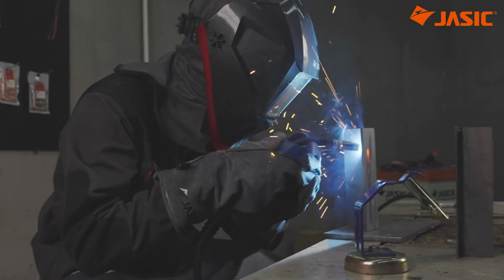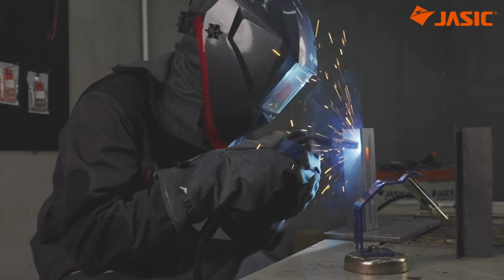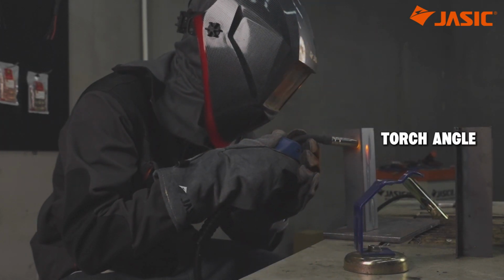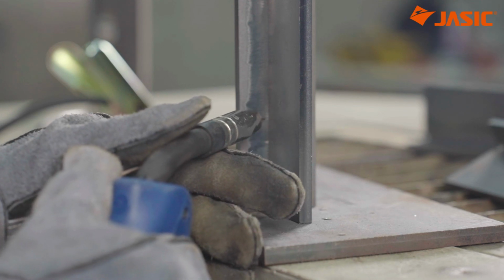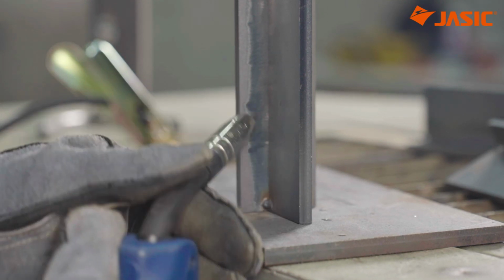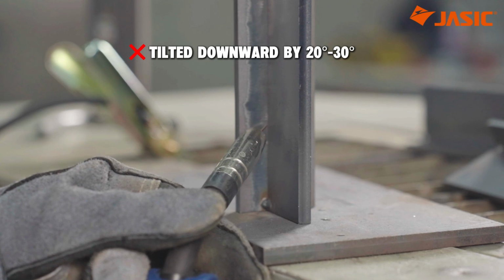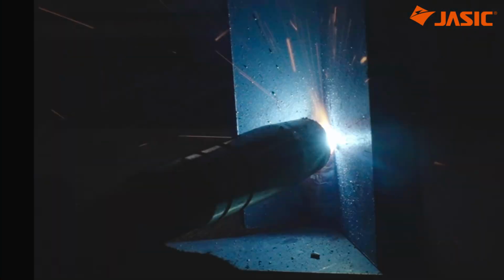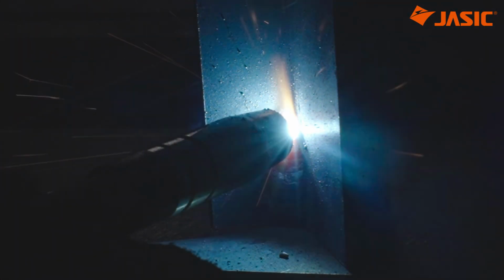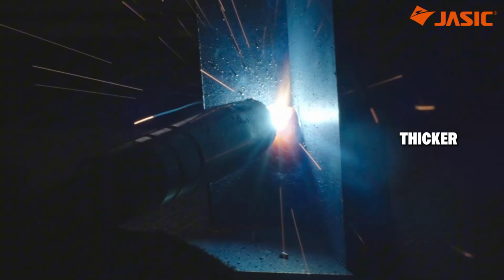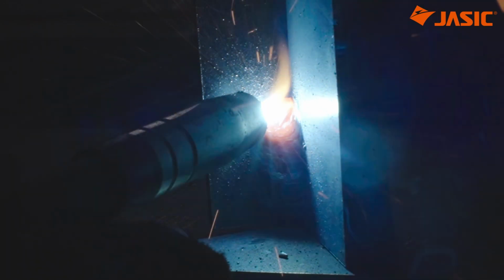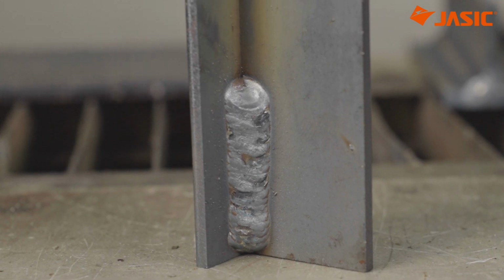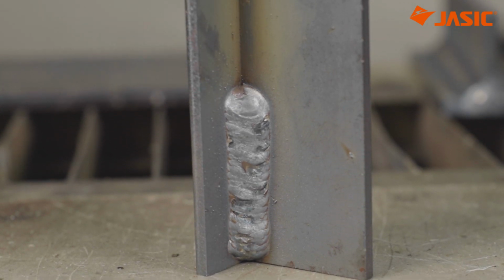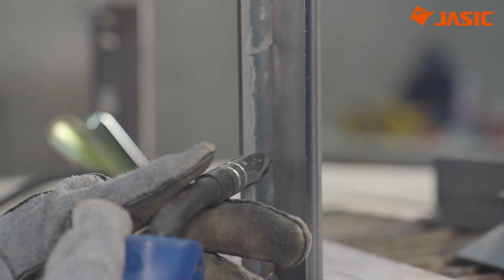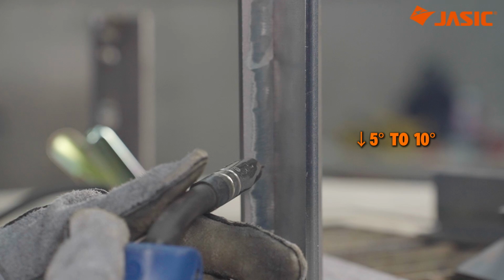If you find that you're having trouble moving the weld upward, the problem is often not your travel pattern, it's your torch angle. A common idea is that for vertical welding, the torch should be at 90 degrees and then tilted downward by 20 to 30 degrees. That's actually a problem. When you push the molten pool upward like this, the weld gets thicker and thicker as you move up, and the thicker the weld becomes, the harder it is to move upward. Eventually, you can end up with a raised or convex section in the middle of the weld. So what's the correct angle? Keep the torch at around 90 degrees or tilt it downward only slightly, about 5 to 10 degrees.